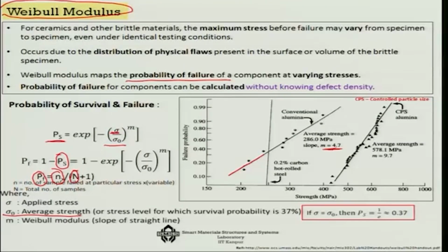In this case, what we have tried to show is that for 0.2% carbon hot rolled steel, you will see that the value of m is very high. It is like a 90° slope, whereas here it has a finite slope. Not only that, the same material, if you reinforce it with alumina, for example, with a controlled particle size, because the particle size variation makes this m lower and lower, you would see that the value of m will be higher than 4.7. The slope is increasing, not of course as high as the hot rolled steel, but it is better than the slope that you would see in this particular case.